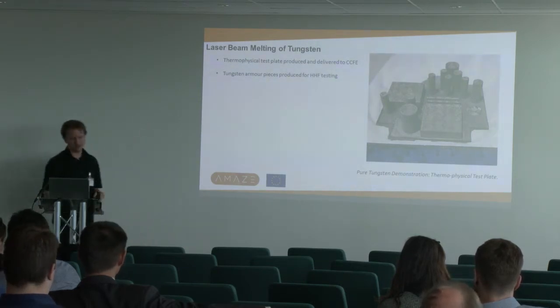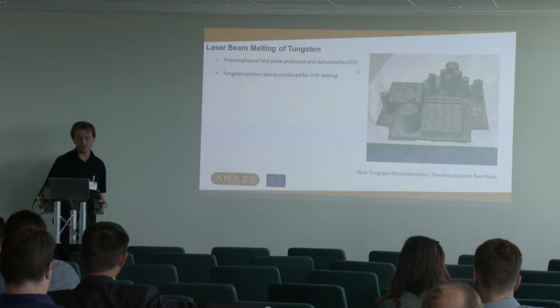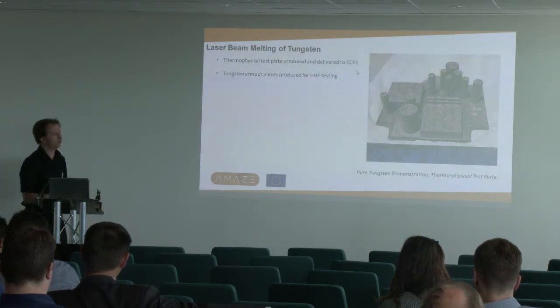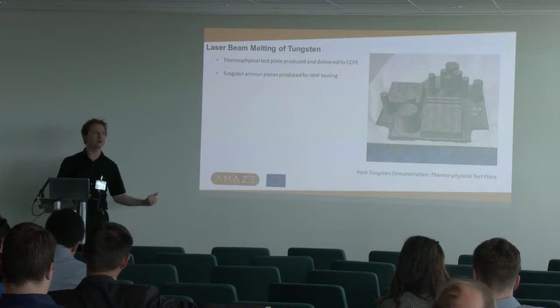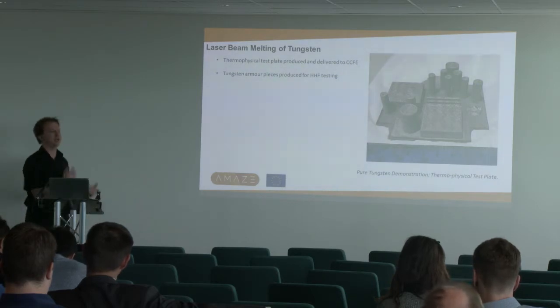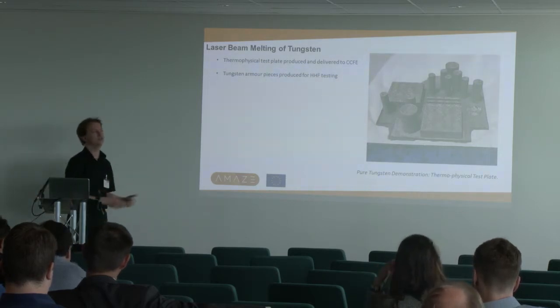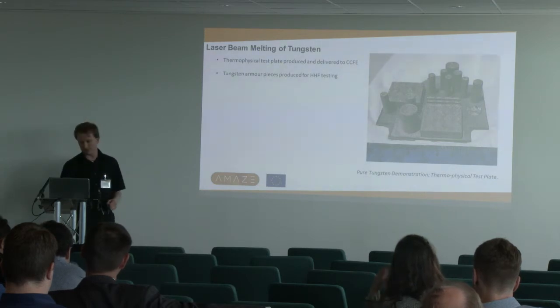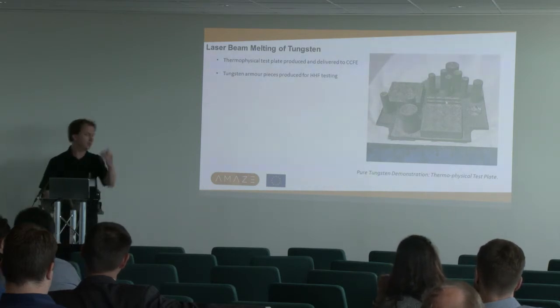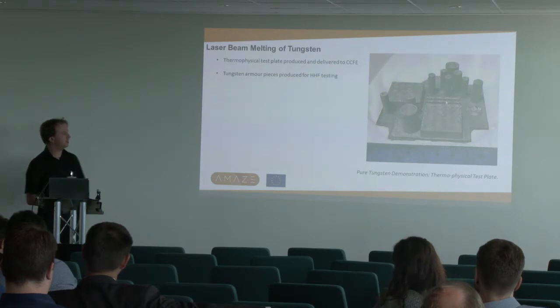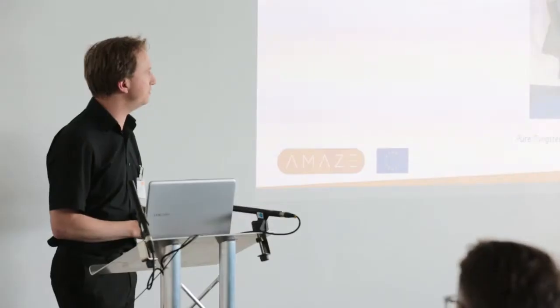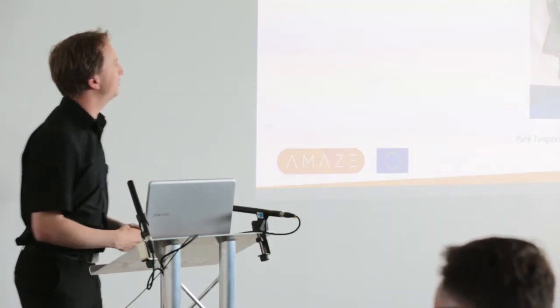Once again, we've produced some parts for CCFE. There are some little bending samples and some thermophysical samples. The point of these tests is so CCFE can benchmark the additively produced material against traditional material. We're passing those samples to them as part of AMAZE. We've also made these big flat squares, which are the armor tiles that Dave was talking about, and we're hoping those are going to be tested in the near future. We've got our fingers crossed that we'll have at least some promising results that they stand up under test.